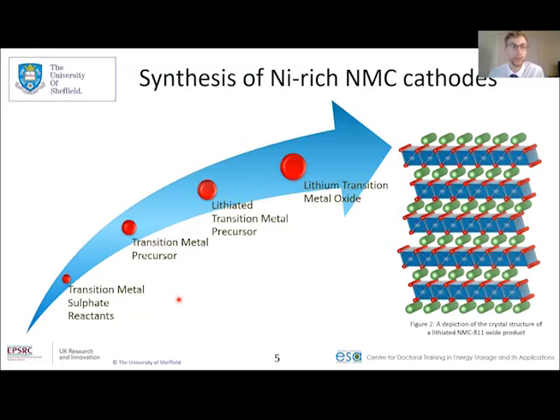And this basic solution reacts to form a hydroxide precursor. It can also form other types of precursors, but primarily in literature, they focus on hydroxide precursors because of the lithium source. This lithium source is added by mechanical grinding to the precursor, typically using either a pestle and mortar or similar sort of physical mechanism, and before furnacing or calcining to form the oxide product, which you can see